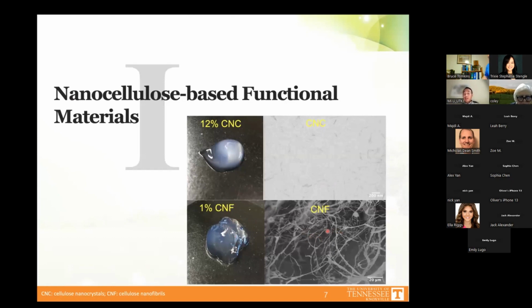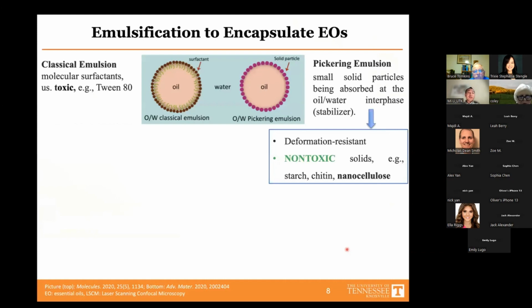And so the CNF under the microscope is much longer. It's about 2 to 100 microns in length, and the width is wider as well, about 50 to 100 nanometers. So what can we do with these nanocellulose? Because they are so small, they can have some special functions or